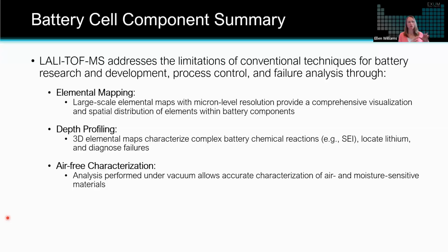Jeff talked about how the entire process is done under vacuum, and what we collaborated with our customers at Stanford on was an air-free transfer vessel that allowed them to actually load those lithium metal samples in a glove box environment, transfer it to our instrument, and then once it pumped down to a high vacuum, the vessel opened and we were able to analyze those samples in an air-free environment.